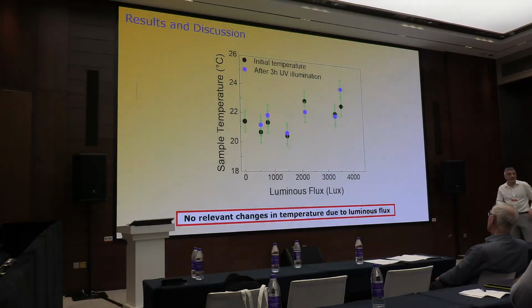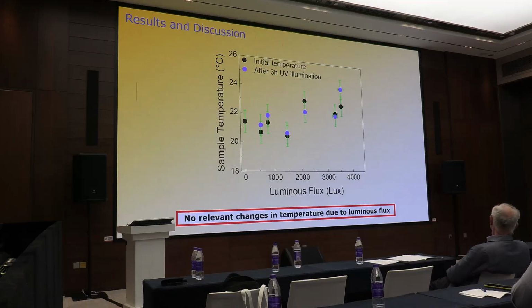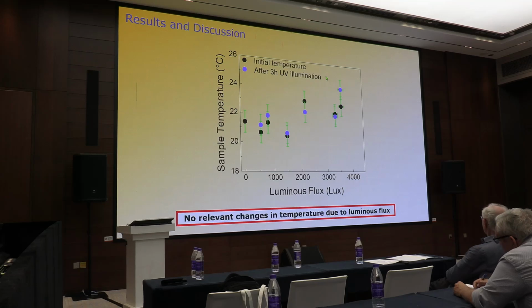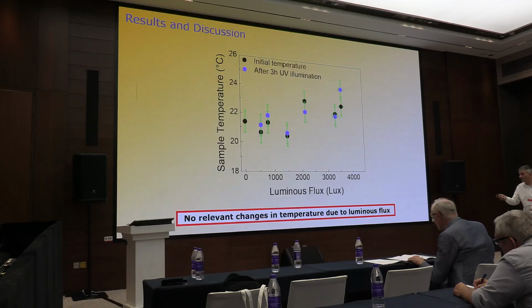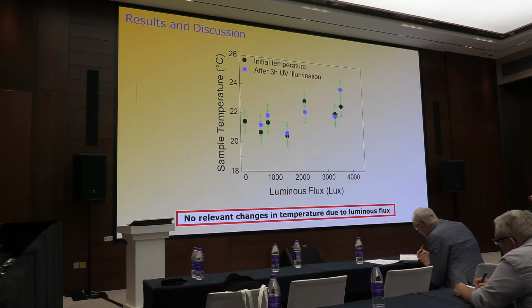Okay, maybe you think you are increasing the temperature, you are changing the temperature. No, the temperature is roughly the same. Here you can see the sample temperature as a function of the luminous flux. There is no big modification. Maybe here is the same, and only this point is a little bit higher. You don't have too much modification of the temperature when you increase the luminous flux. No relevant changes in temperature due to luminous flux.